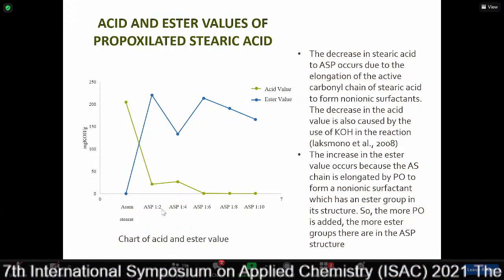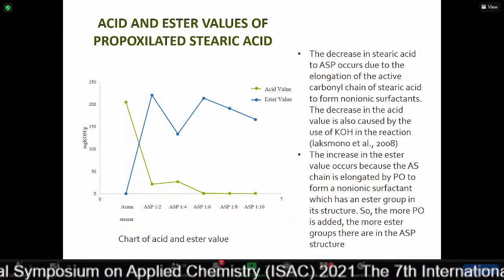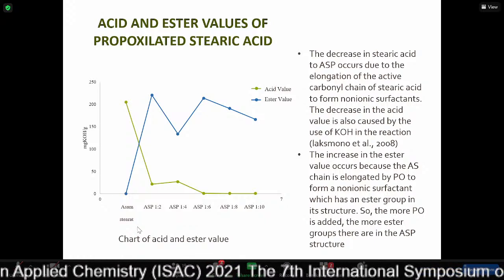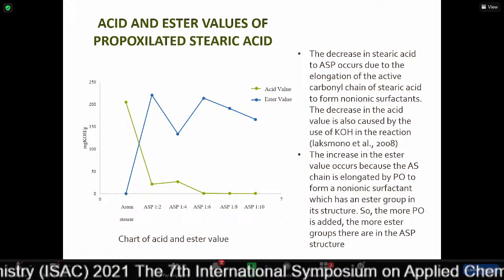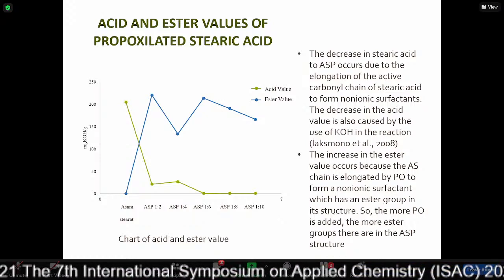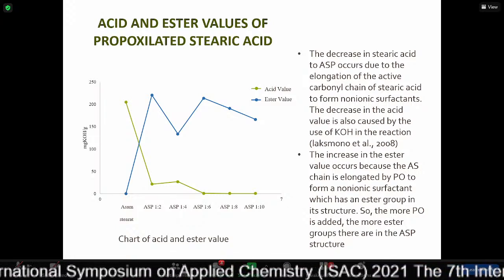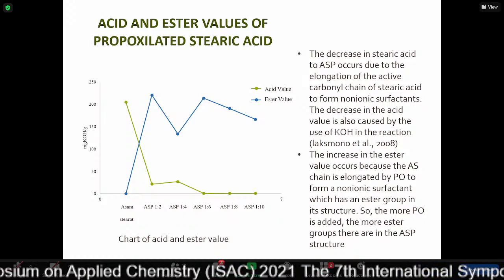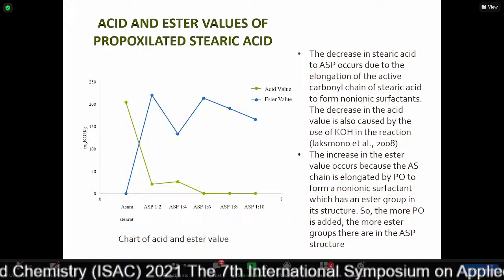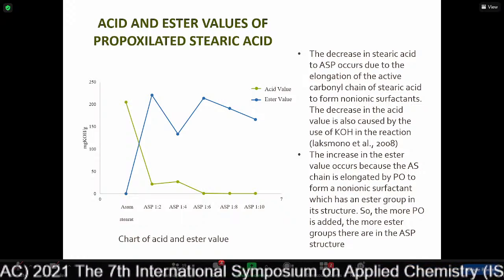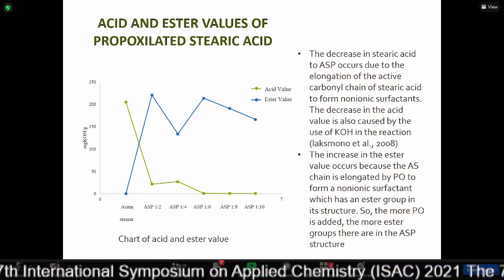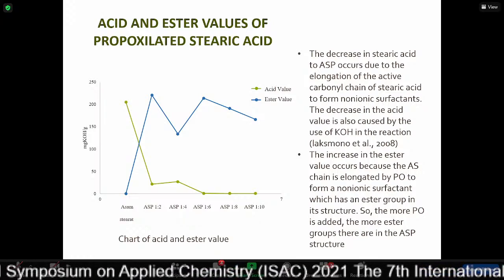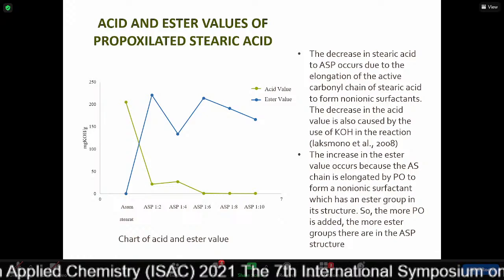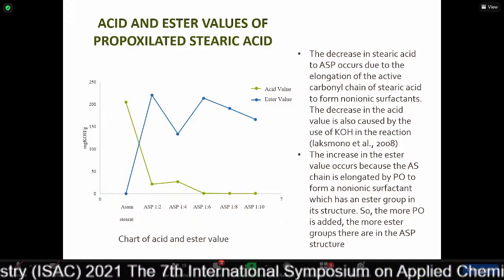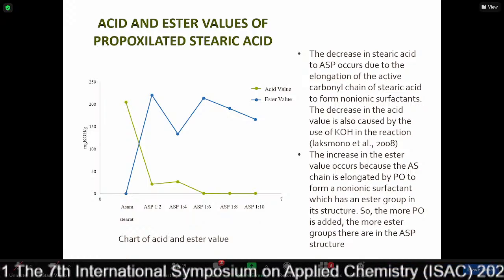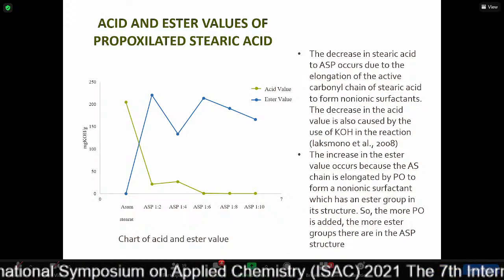So we can see here the decrease of stearic acid in this stearic acid propoxylation occurs due to the elongation of the active carbonyl chain of stearic acid to form non-ionic surfactant. The decrease in the acid value is also caused by the use of potassium hydroxide in the reaction. And the increase in the ester value occurs because the stearic acid chain is elongated by the propylene oxide to form a non-ionic surfactant which has an ester group in the structure. So the more propylene oxide is added in the reaction, the more ester groups will be produced in the stearic acid propoxylation structure.